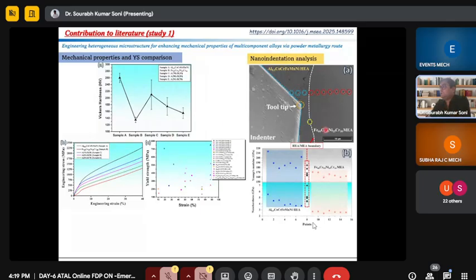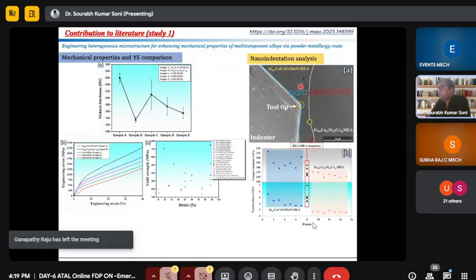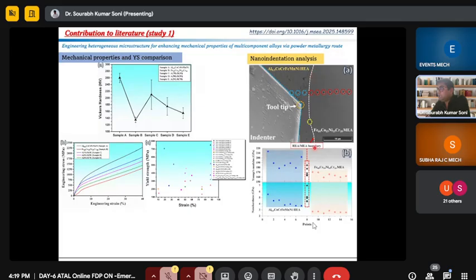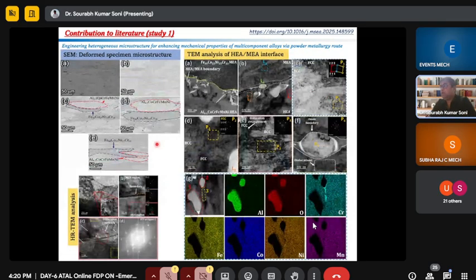This is the nano indentation analysis. This is the HEA specimen. This is the HEA surface. This is the MEA surface, and this is, we can say, the interface. So I have analyzed the nano indentation at the HEA phase, MEA phase, and interface also, so that we can relate the trend of hardness. Like here, aluminum HEA and Cantor HEA are showing more hardness than FeMEA. So you can relate this kind of property.